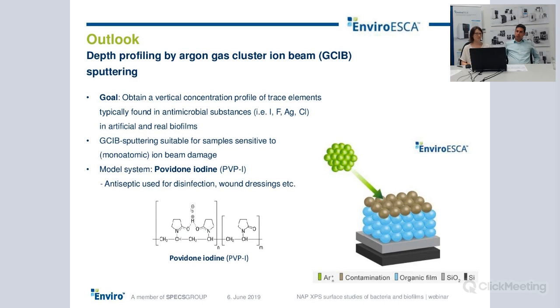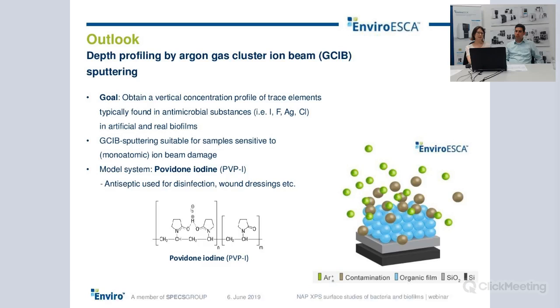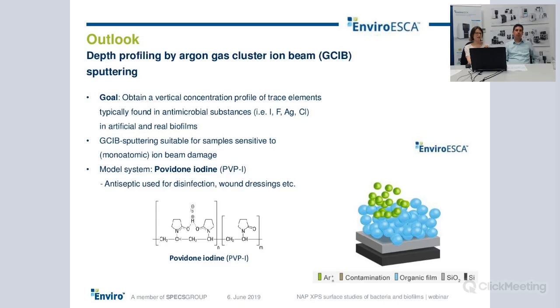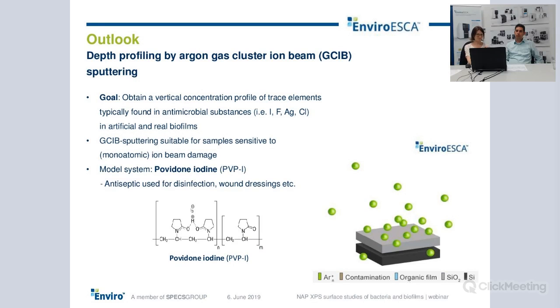So as a short outlook for what we want to do next, or what we are doing already, our interest is that we use this well-defined model system and take it one step further. Then we want to add antimicrobials and detect the vertical concentration profile of these elements. Antimicrobials typically consist of elements like iodine, fluorine, silver, and chlorine, and they can be distinguished from the organic matrix. And for this, GCIB sputtering, or argon gas cluster ion beam sputtering, is a suitable method in combination with XPS. In that method, you are bombarding the sample with argon clusters, and the argon clusters then remove atomic layers of the sample, and in between you acquire XPS spectra to detect the depth-dependent spectra.